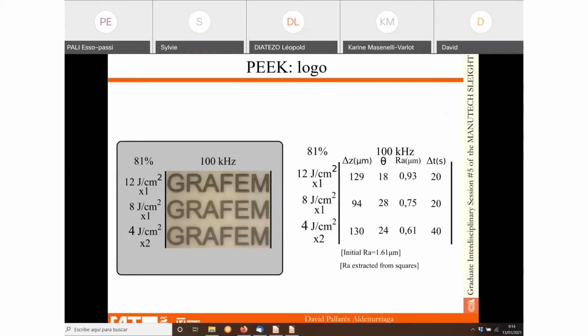For example, at 12 joules and 4 joules, we get a sharp edge because we got approximately the same depth, but this one is sharper, but the roughness is higher at high fluence, though the time is less. Actually, it takes double the time with 4 joules to reach the same depth.